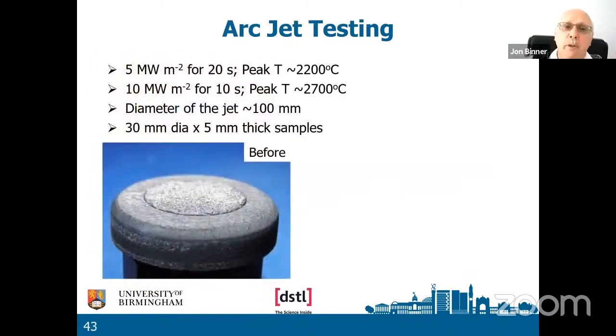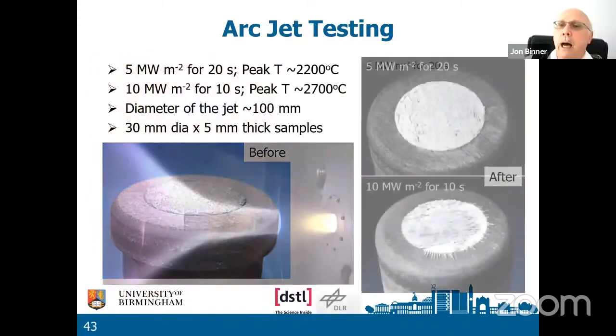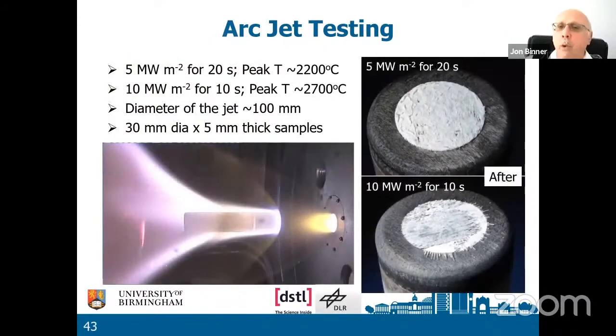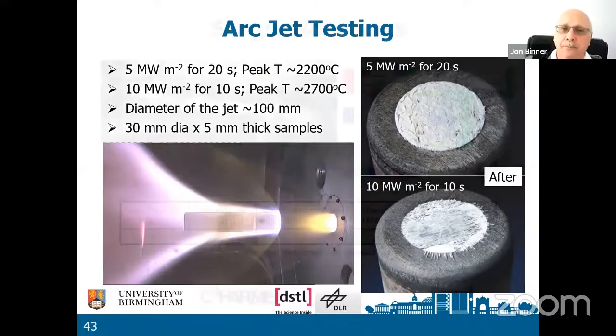So here's our samples at the beginning, and there is an image of the sample being tested, and here are the images of the sample after the test. Very short times, 20 seconds, 10 seconds, but in that bottom one at 10 megawatts per meter squared, you can see splashes of what was molten hafnium after the test.